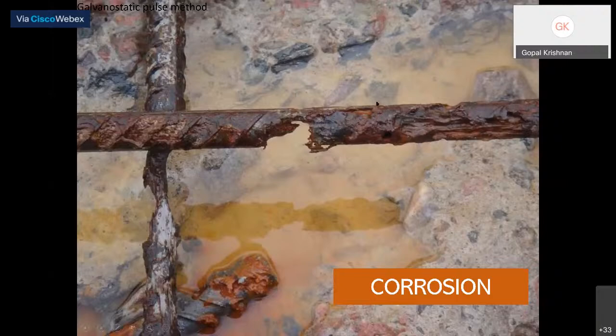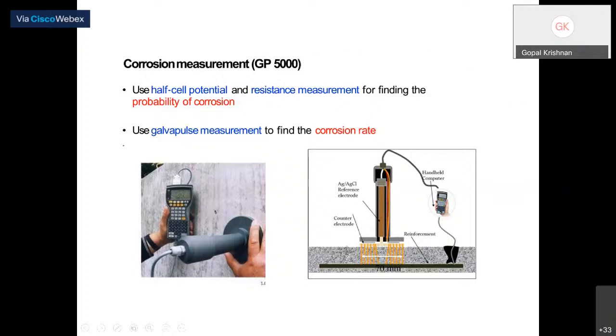For measuring corrosion, we use the GalvaPulse GP-5000, which is a combination of half-cell potential and resistivity, and also gives the corrosion rate in real time. The three properties you can get from this instrument. Mainly, we try to understand the corrosion rate.